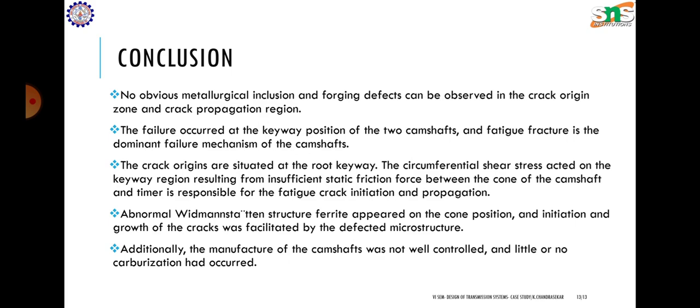And also abnormal Widmanstätten structure ferrite appeared at the cone position, and the initiation and growth of cracks was facilitated by the defective microstructure. So this defective microstructure near the cone is also a reason for initiation and growth of the cracks.